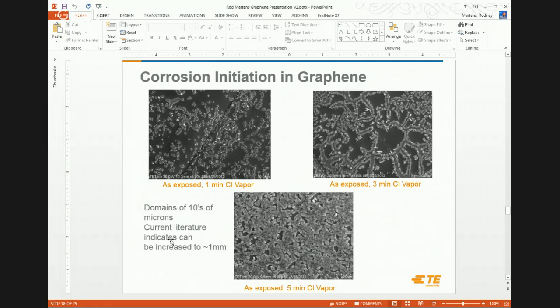So we know then that it's not perfectly impermeable, because you can have corrosion that initiates at those boundaries and then comes up and creeps over the so-called good graphene, and then you end up back where you started. We have a film covering the entire surface.